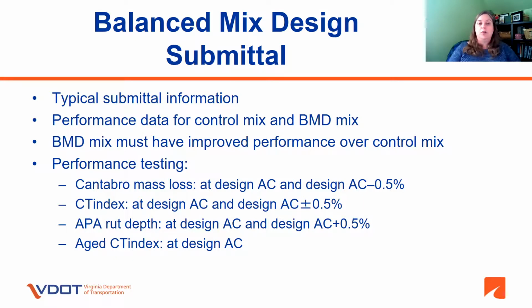For performance testing, you're going to be submitting each result at multiple asphalt contents. Cantabro mass loss is submitted at design asphalt and design minus 0.5%. CT index will be submitted at design AC and design plus or minus 0.5%. APA rut depth will be submitted at design and design plus 0.5%. What these do is give an idea, as asphalt content varies, which we know it does during production, what we can expect in terms of the performance testing results.